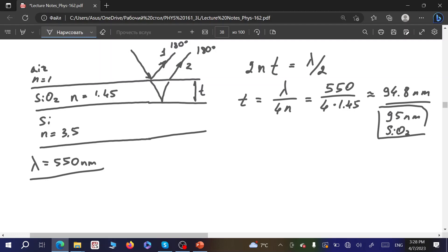This is the thickness of silicon dioxide which should be deposited on top of silicon in order to get minimum reflection — specifically zero reflection from this stack for incident light at 550 nanometers. If the incident light is white light like sunlight, all other wavelengths will still reflect since they do not satisfy this destructive interference condition. However, specifically 550 nanometers — corresponding to the highest solar intensity and the peak of photopic human eye sensitivity — will not be reflected and will pass into the silicon substrate to generate photo-carriers and contribute to photocurrent.